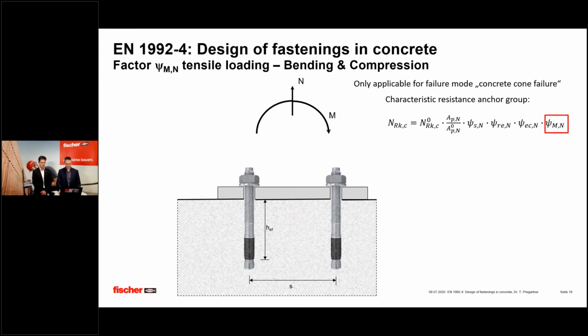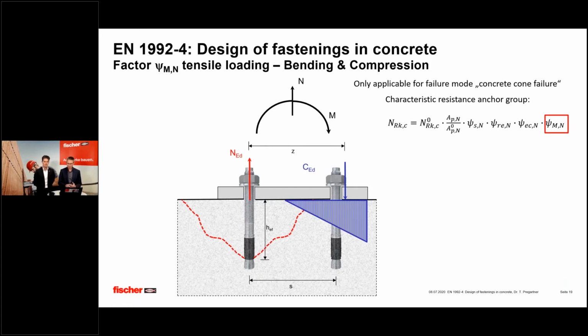Now, if you have a bigger bending moment compared to the tension load, you get this picture where a larger area is compressed under the fixture, and this compression zone more or less influences the concrete cone of your pulled anchor, and like that you get an increase of the characteristic resistance. The equation for the factor ψM,N is now shown on the slide. It is a function of the embedment depth and the inner lever arm.